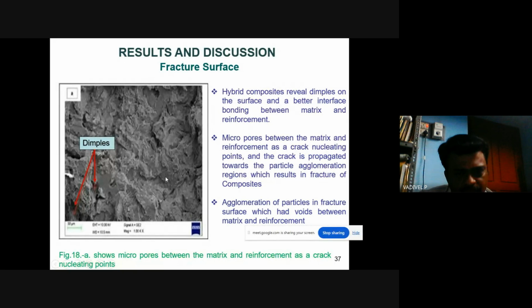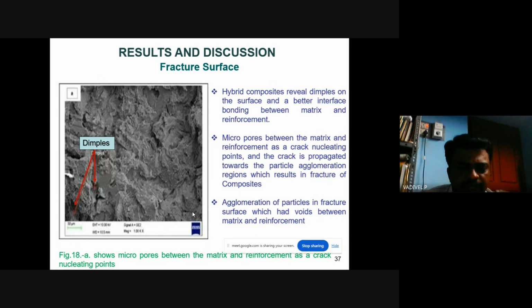Because of these micro pores, the crack is initiated at some point, and it tends to break the sample. The agglomeration of the particles on the fracture surface had voids between the matrix and the reinforcement.